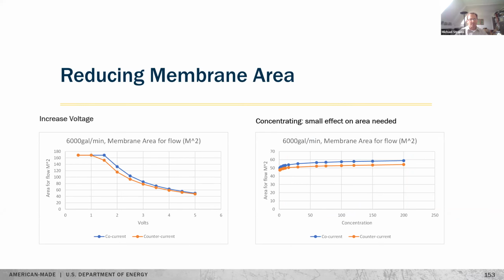Going to the right graph, we ask what happens as you try to concentrate the product. Basically, what you're doing here is you lower the flow in the product channel. So at a factor of 200 in concentration, instead of flowing 6,000 gallons per minute, you're flowing 30 gallons per minute of hot water. And we see only a modest increase in membrane area needed. This is because the electrochemical activity across the membrane has a relatively small effect. It is not the driver in the system. It is pushing the stuff through the membrane.